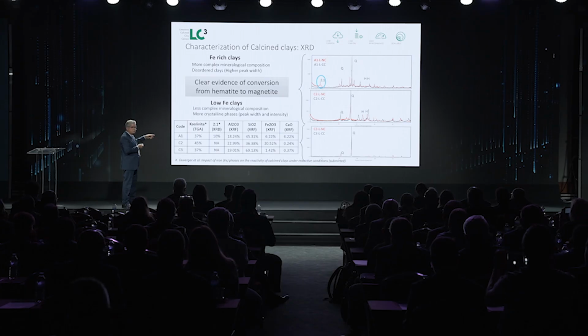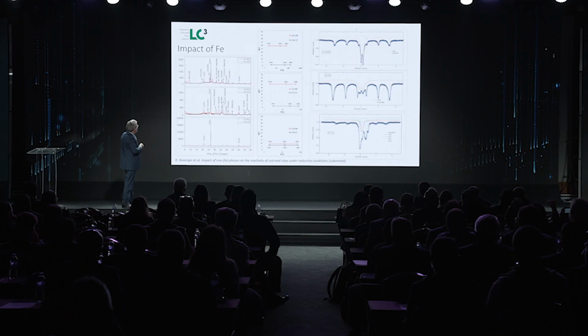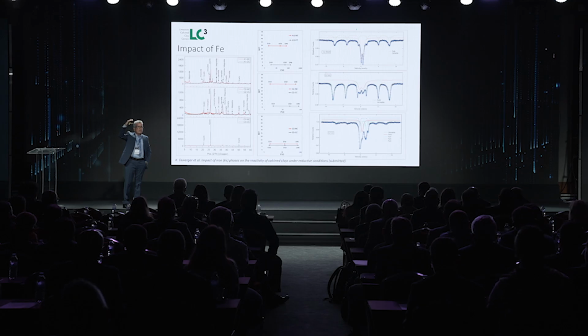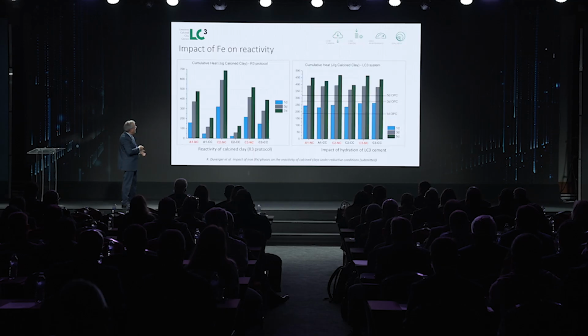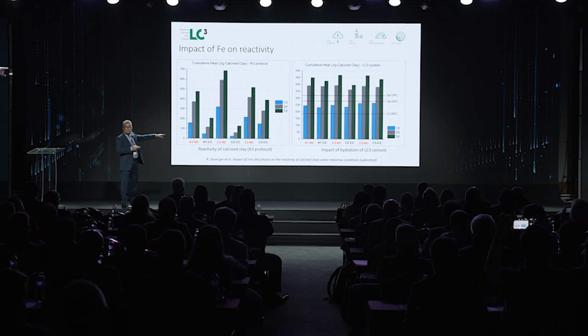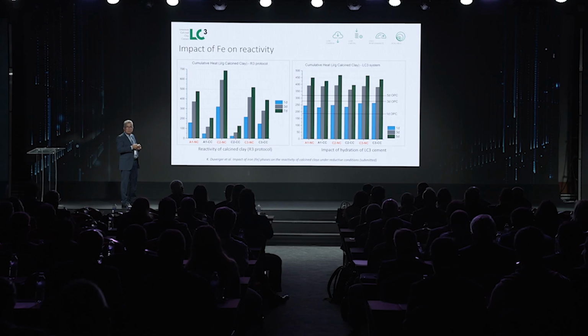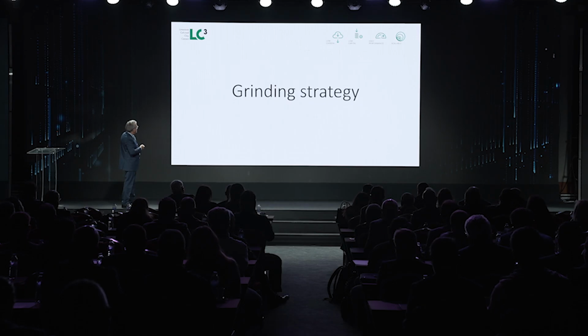This is a result of testing different clays with different iron contents, different things. What we're seeing is that when you have a very high iron content, I'm talking about higher than 10%, you begin to see a drop in the specific surface that can basically compromise the reactivity of the material. But when you go and measure in cementitious system, even for the higher iron content, the impact is not very relevant in terms of the reactivity.